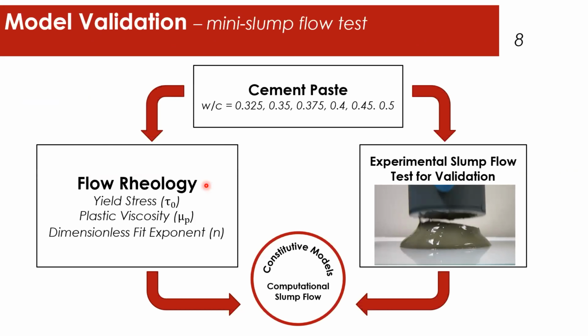So what I have already done is I made the paste, I did the flow rheology and extracted the yield stress, plastic viscosity, and the dimensionless fit parameter for the Herschel-Bulkley model. But to understand how the rheology of cement paste works, a good test is to do a slump flow test. The slump cone is a simple device. It is conical, filled with the cement paste, and the cone is lifted such that the cement paste slumps under gravity. So here I did the experimental slump flow test and compared the experimental outcomes with constitutive model outcomes.